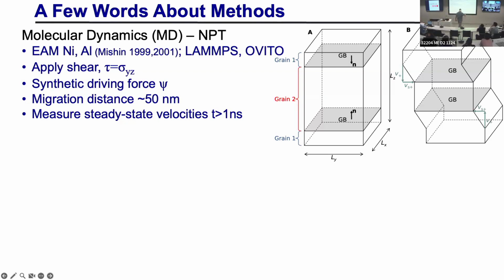Okay. So I will show you some results where we drive the boundary by putting on this chemical potential difference, the jump in chemical potential across the boundary, which we call the synthetic driving force, or by applying a shear. I'll average the data over boundary migration over distances of at least 50 nanometers. The simulations may take anywhere from nanoseconds to many tens of nanoseconds, depending on what I need to get good enough statistics. Okay, so that's the first part.